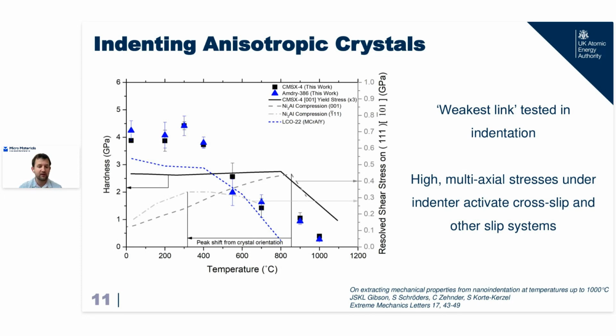And you can see here the gray dashed lines are what happens when you test those high strength gamma prime precipitates in different crystal orientations. And actually, the bar 111 orientation softens past 300 degrees. And so this is exactly what we're picking up with the indenter. It's simply a crystallography effect where we're getting softening by having slip on our weakest available slip system.